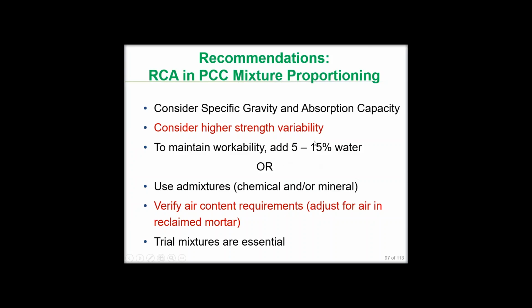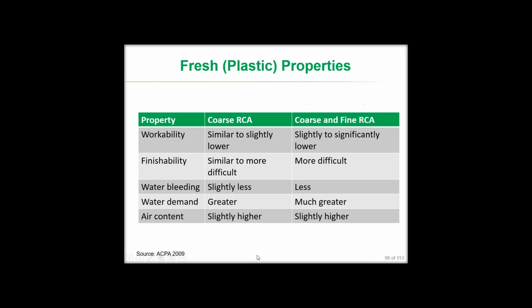To maintain workability, we may see some higher water contents, and of course if you don't want to increase the water-cement ratio, that means you're going to be using higher cementitious contents as well, which might mean higher shrinkage in that mix, and that needs to be considered in the behavior of the mix and in your design procedures as well. Other approaches, of course, the use of chemical and mineral admixtures, and making sure you get the right amount of air content. If there's much reclaimed mortar used, you'll typically see higher indicated air contents because the air in the mortar will be reflected in the air pot test as well. So trial mixtures are always a good idea.